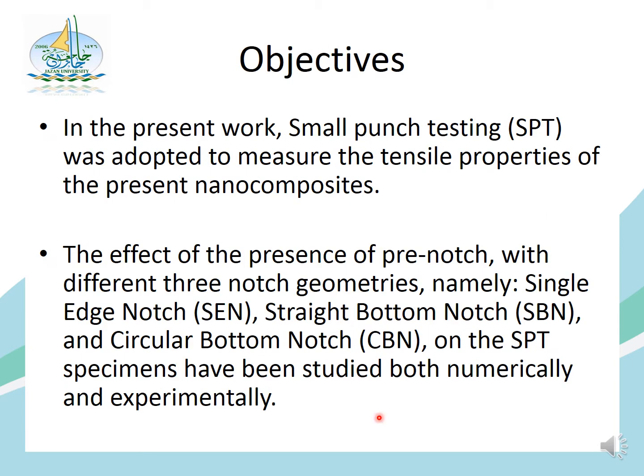So, the main objective in this study is that the small punch test was adopted to measure the tensile properties of the present nanocomposite, and the second main objective is the effect of the presence of a pre-notch with three different notch geometries: the single edge notch, which is the SEN, the straight bottom notch, the SBN, and the circular bottom notch, which is the CBN, on the small punch specimen. These have been studied both numerically and experimentally.